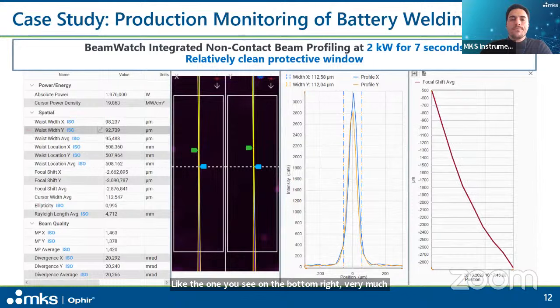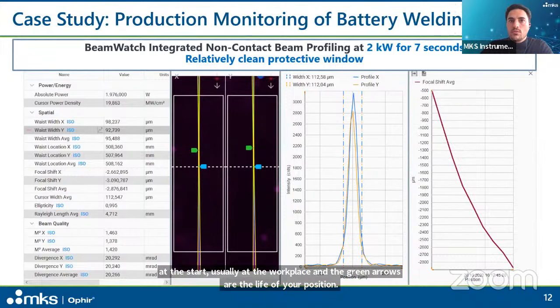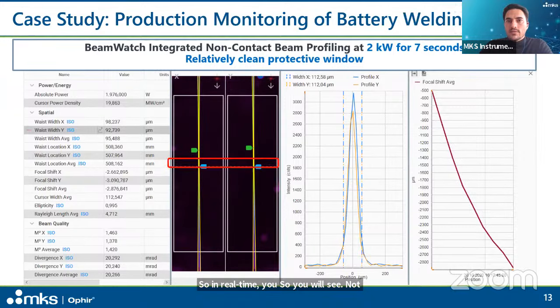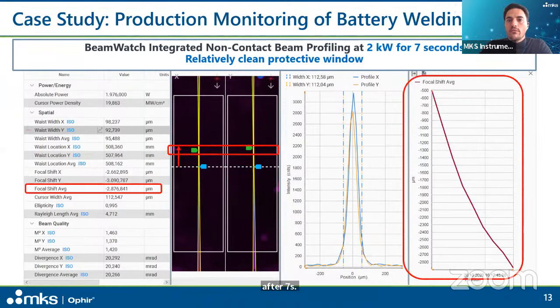So now let's jump to an interesting use case or case study here. In that case, we're speaking of battery welding, more specifically busbar welding, aluminum, using a 2 kilowatt single mode laser. And here you see a BeamWatch Integrated measurement of a system with a relatively clean protective window on the optic. And this is a 7-second measurement at 2 kilowatt. So in the background, what you can see is a beam profile seen from two axes, X on the left and Y on the right. And the two blue arrows indicate the focus at the start, usually at the workpiece, and the green arrows are the live focus position, so in real time. So you will see that in this case, after 7 seconds, we have a focus shift of just under 3 millimeters.